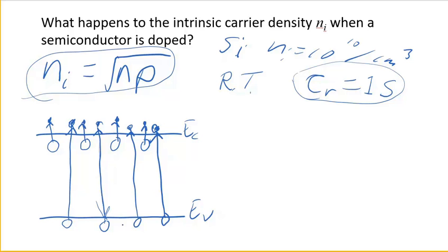There are going to be fewer holes than there were before, because eight times per second you lose a hole, and four times per second you gain a hole. In equilibrium, you're going to have fewer holes. You won't have eight electrons up here in the conduction band, because you're going to keep giving up electrons to destroy holes, right? So it costs you a few electrons. It does. It'll cost you two electrons to get rid of two holes. Thermal equilibrium does have a penalty on electrons, but you have a lot more of them. So you don't care so much about it. But you lose a lot of your minority carrier concentration.